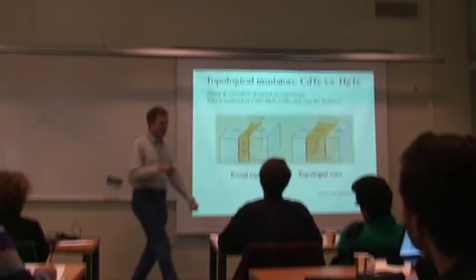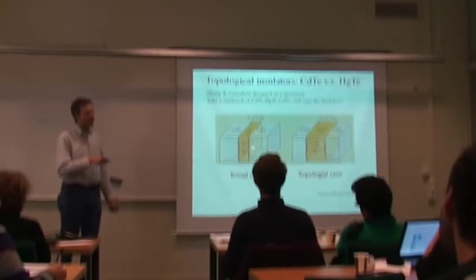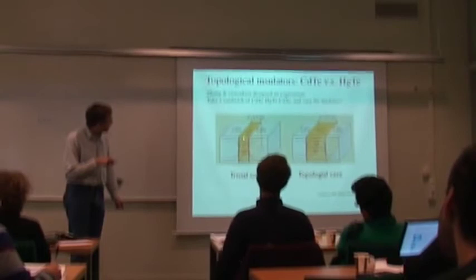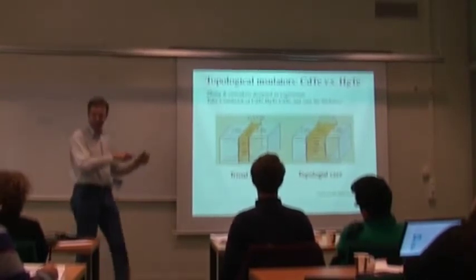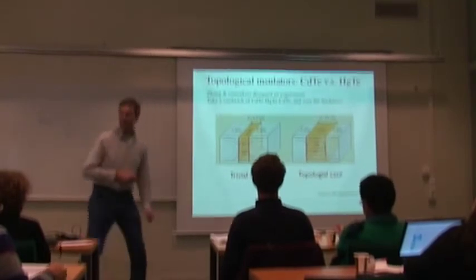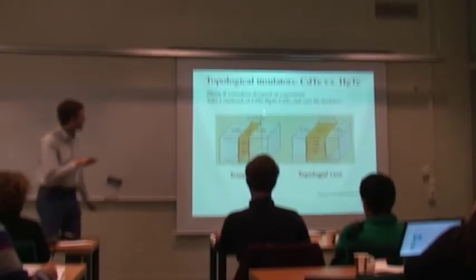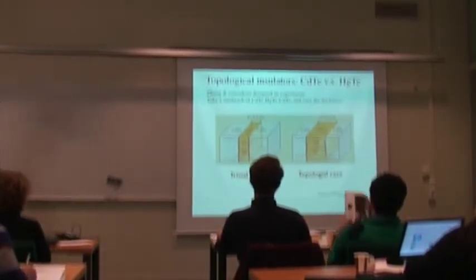One of the nice things about this experiment is that we can actually tune the thickness and see that at a certain thickness, for very thin layers, you see the normal behavior of an insulator. Then all of a sudden, when the thickness is big enough, you see the other behavior. Using this thickness as a control parameter was a really interesting way of doing things. Why do you need the cadmium?